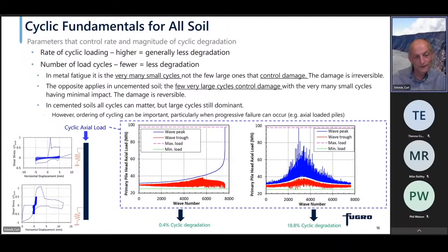In metal fatigue, if you've talked to structural engineers about cyclic loading, it is a very different world. In metal fatigue, it's the very many small cycles, not the few large ones, that control damage. And this damage is irreversible, a bit like with the calcarenite, you've got irreversible damage. The opposite applies, though, in uncemented soil, irrespective of whether it's clay, sand or silt. It's the few very large cycles that control the damage that is going to occur. And generally, the very many small cycles have minimal impact. And this damage is reversible, as we discussed before as well. So they are really quite opposite phenomena.